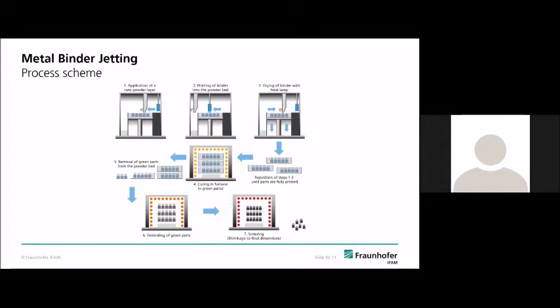These parts are inside so-called build boxes. And the whole build box is put into a curing furnace and the binder is cured. So it's a kind of pre-step on its way to a three-dimensional part. When the parts come out of the curing furnace, you have so-called green parts. So metal powder glued together, stuck together with a binder.